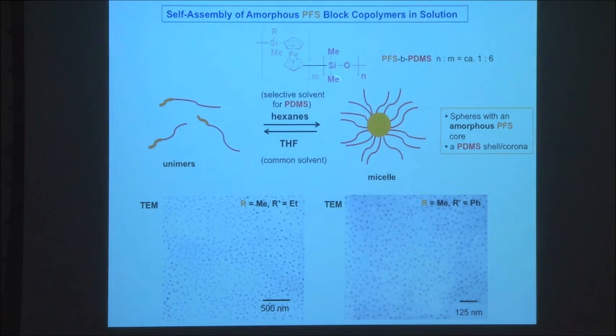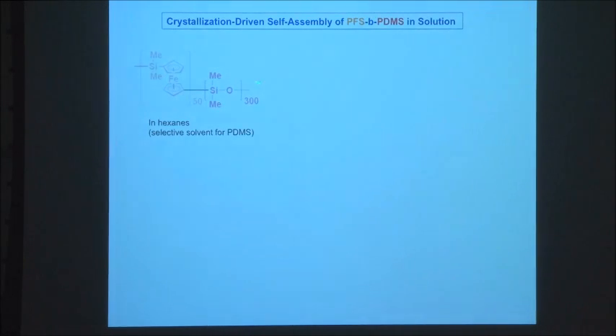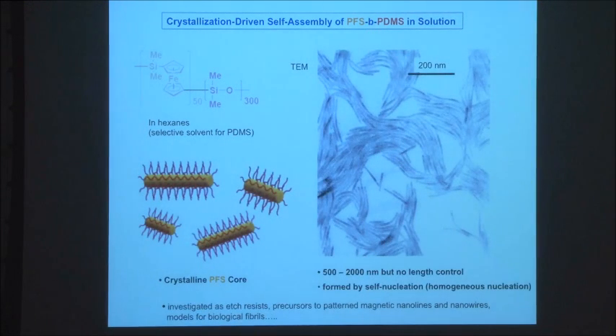So what happens if you take exactly the same material, do exactly the same experiment, but instead of having the amorphous PFS block, you have one with two methyl groups on silicon that will crystallize, so dimethyl PFS. So here's the structure of this. It's identical, except you've got two methyl groups on the silicon for the core-forming dimethyl PFS block. You can put this in THF and then add hexanes. And what you find is, instead of getting spheres, you get a totally different morphology. You get cylinders. And the cylinders are of different length. You can see some short ones here and some very, very long ones. So there's no length control here. The lengths vary from about 500 to 2,000 nanometers.